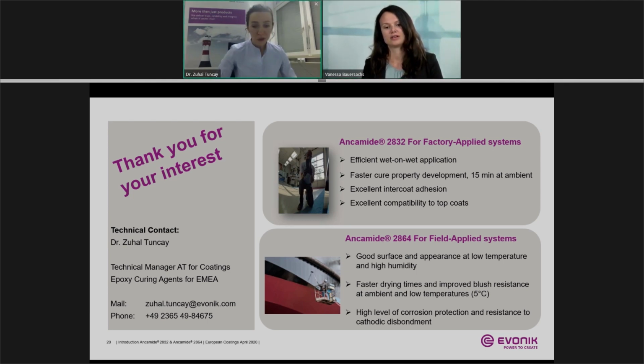For low temperature curing, we recommend the product 2864. And in this case, it will be dry after 30 minutes. And then it depends on what kind of top coat you would like to use. And I would say the time for return to service is up to the top coat. But I guess that will be something between 24 hours or 48 hours.